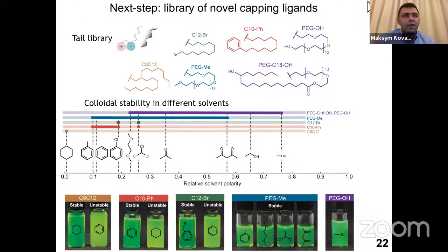Now, with this knowledge, we have tested the whole library of ligands. So we kept the PEA-based zwitterionic phospholipid group, and we engineered a lot of different organic residues. And this is the first time that you can have perovskite nanocrystals dispersible in basically every solvent that you may come up with, except water, because in water the material itself dissolves, the perovskite material. But now you can disperse perovskite nanocrystals in alcohols, in acetone, or in very apolar solvents. And you simply accomplish that by the group which you bind to your phospholipid.